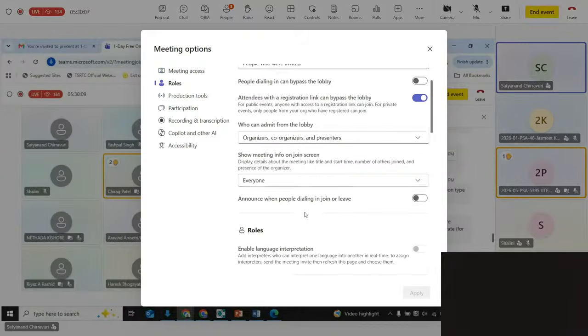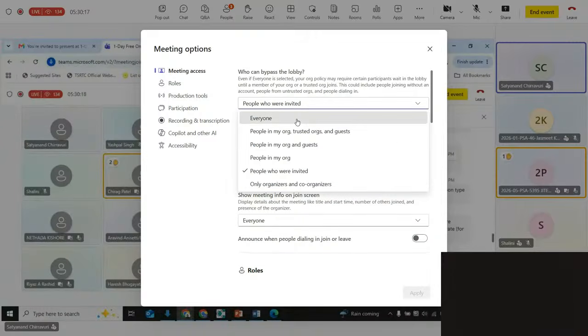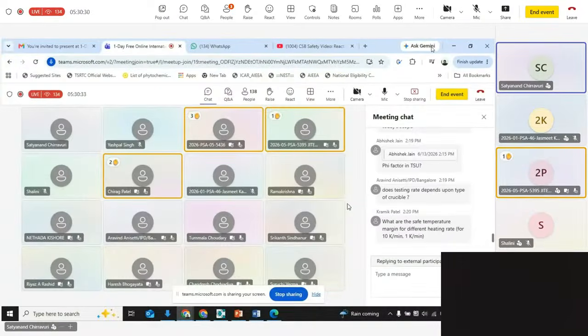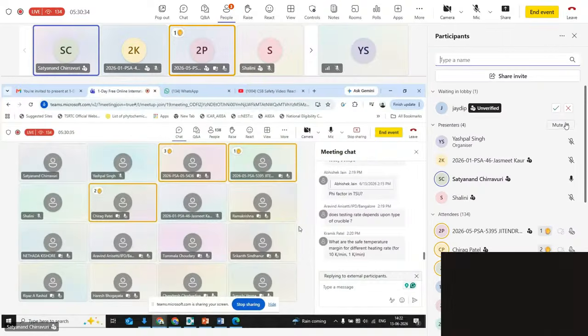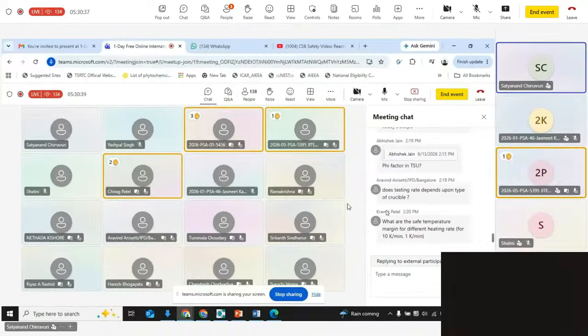Does testing rate depend upon type of crucible? Yeah, the answer is no, as I said. What are the safe temperature margins for different heating rates? No. See, first of all, there is nothing called safe temperature margins. First of all, you actually do it at 10 degrees centigrade per minute, and then you get a thermal event, and you look at the onset. Then if at all you feel it is very alarming for you and it is almost nearer to your operating conditions, that is where you have to do it at a slightly lower temperature rate. And if at all the lower rate onset and 10 degrees centigrade onset have a difference of only 2-3 degrees centigrade or 5 degrees, it doesn't matter much, right? So there's nothing to worry about.